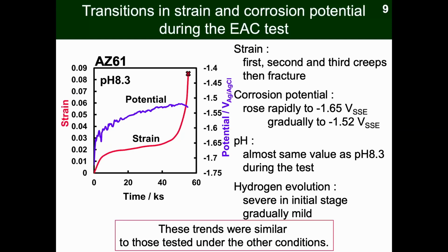On the other hand, we didn't put pH in this figure, but pH is almost the same value as the initial value. So pH was kept. And we see the hydrogen evolution. Hydrogen evolution severely occurred in the initial stage and gradually became mild. So this trend was very similar to the trend under the other conditions.